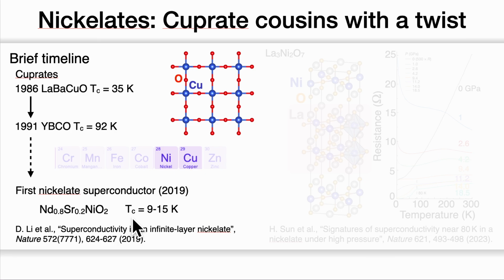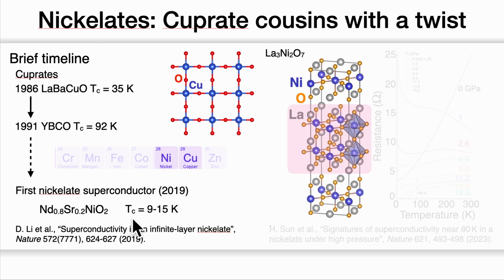However, the intriguing discovery came in 2023 when another nickelate, LNO, was put under pressure. Here we show the structure of LNO, which has two nickel-oxygen planes. As we see here, they are connected by oxygens. The two planes are believed to provide more electron pairing to achieve high Tc.